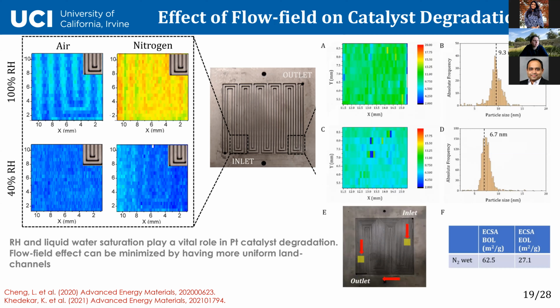How are flow fields currently made in industry? Well, they're being stamped. You have two thin sheets of titanium, you stamp them, and then you weld them together. It's a bipolar configuration, you have anode, cathode. In the middle channel, you have coolant flowing through it. So current technology is limited by the stamping process. You cannot really stamp really fine features. You're going to break the material, right? So it's either stainless steel coated by titanium, or it's titanium coated by graphite because you form titanium oxide. So realizing 0.5 millimeter lands is still probably not feasible. Mostly stamping has around 0.8 millimeters, 1 millimeter or so. But something interesting to look at in the future.